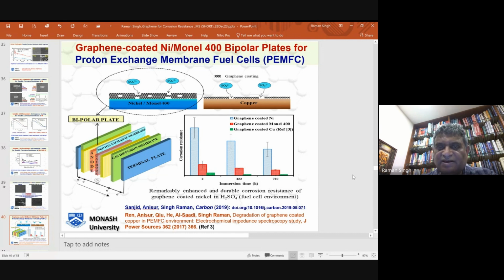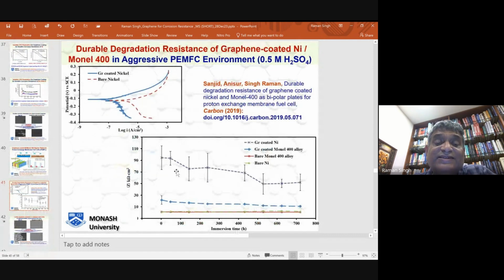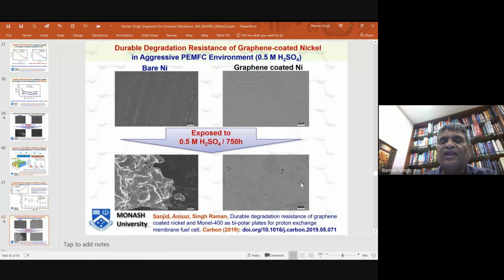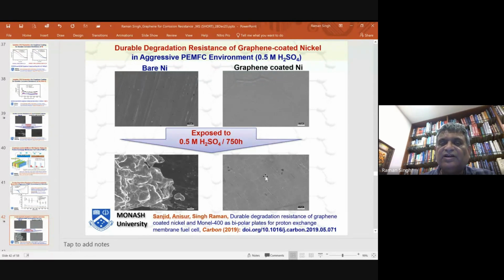Then we started to show that it is long term, it is durable corrosion resistance in this highly aggressive sulfuric acid environment, and corrosion resistance sustains for more than 700 hours. And again, post-corrosion analysis: bare nickel in this highly corrosive solution will be finished in no time, whereas graphene-coated nickel showed very good corrosion resistance, and post-corrosion imaging confirmed that.